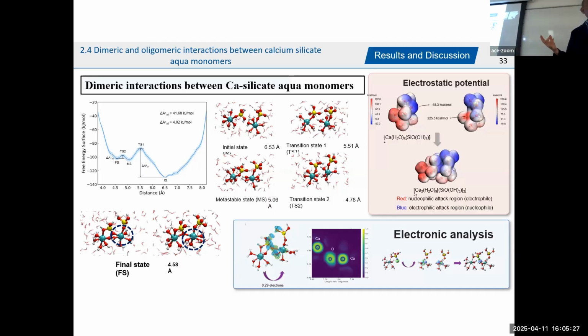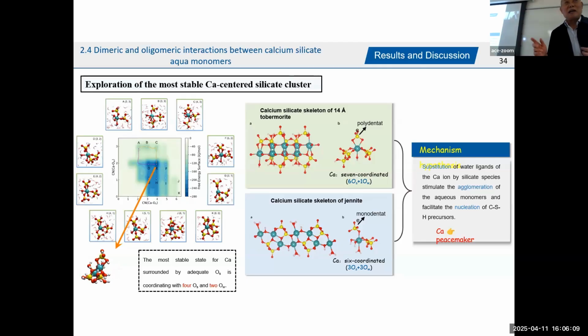This part I am going to utilize because currently we need to reduce carbon dioxide. One way to reduce carbon dioxide is to eliminate Portland cement. But if we eliminate Portland cement, we need a binding material. So I can get the calcium and the silicate from natural sources and also from industry waste. Then we use that reaction to form so-called secondary CSH. So this is still good, but I still ask my student to continue to work on the surface reaction, because that will be more realistic for the formation of this.